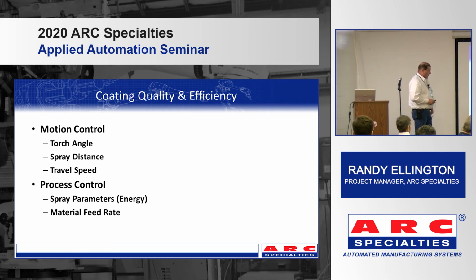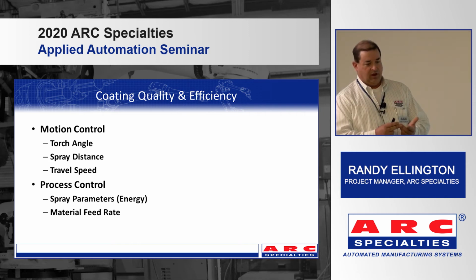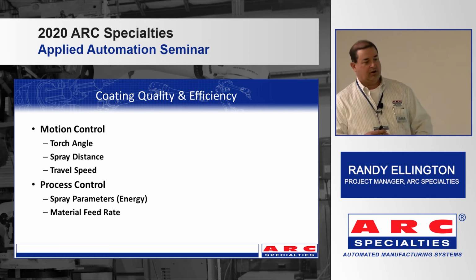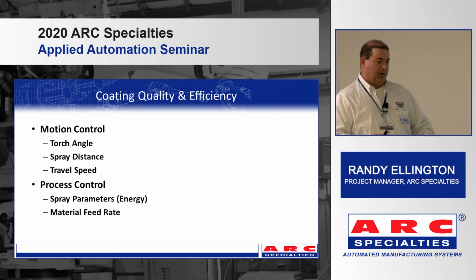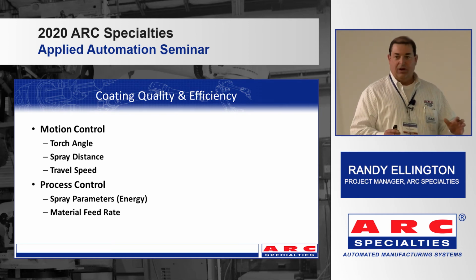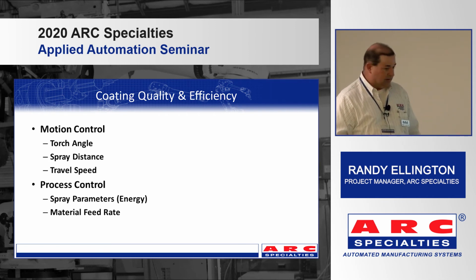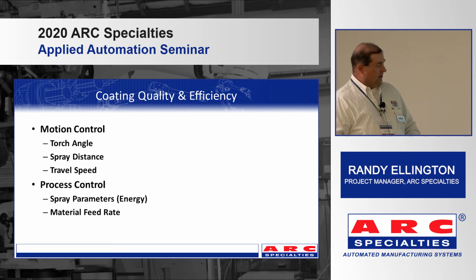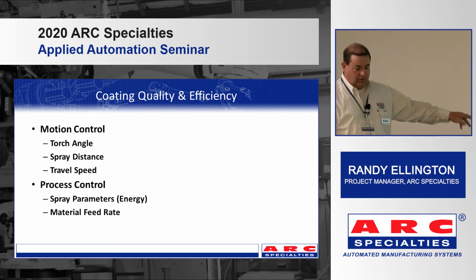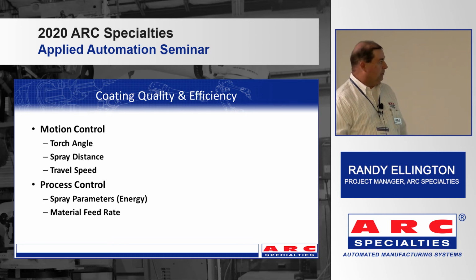And then the other one, the process control. Your spray parameters. We were looking at plasma a while ago. I briefly went over it, but you've got voltage, you've got amperage, you've got a primary gas, a secondary gas, the pressure coming in, your material feed rate, how many pounds per hour you're spraying, as well as your carrier gas pressure and your carrier gas flow. I forget how many different parameters there are with plasma, but you change one of them and it gets a little bad. You change 2 or 3 of them and it goes to pieces on you, and you're trying to figure out which ones just went out. Different combinations make it really hard to maintain a good coating process. So by automating, you control motion control, and you control the process control. Keeps everything a little tighter, makes it run more efficiently.